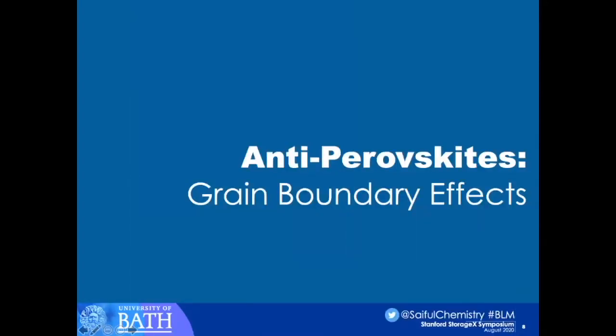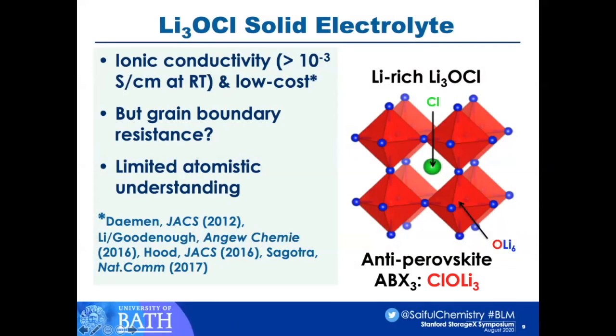So let me move on to these antiperovskites. They're interesting materials. They were looked at by Zhao and Daemen a few years back. They found high ionic conductivity, around 10 to the minus 3 Siemens per centimeter at room temperature, in relatively low cost materials. John Goodenough has been looking at them and various others. There has been some debate about the levels of conductivity and their migration barriers. And some of the debate revolves around the possible grain boundary resistance. But there's always, as with a lot of grain boundary work, limited atomistic understanding, real quantitative understanding of grain boundary effects.